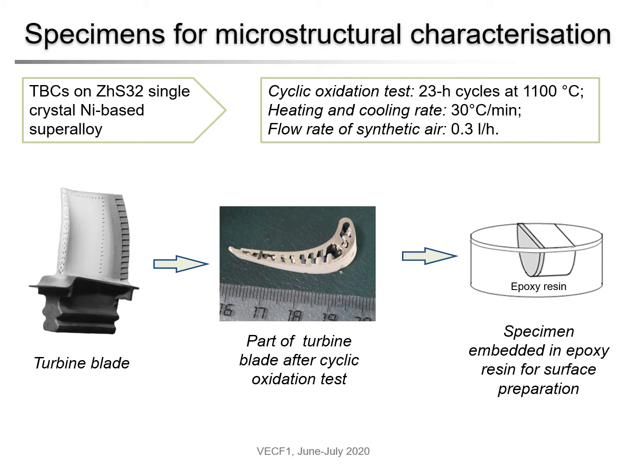The specimens of a turbine blade of single crystal nickel-based ZhS32 superalloy coated with TBC obtained by electron beam physical vapor deposition, after cyclic oxidation test at 1100 degrees C, were cut and prepared for microstructure observation using conventional techniques.